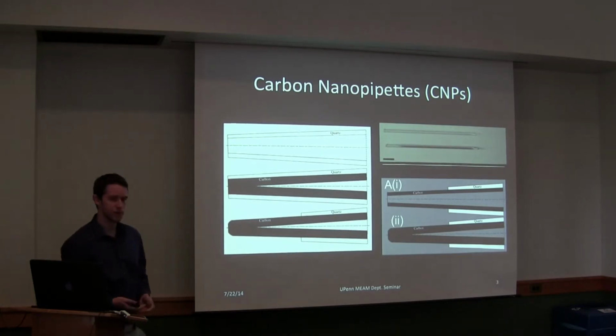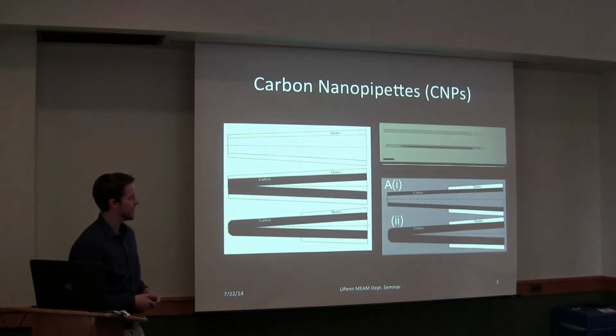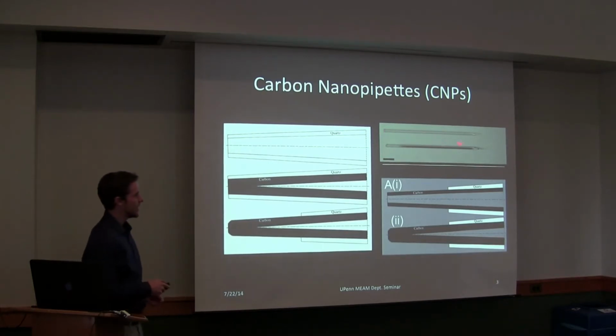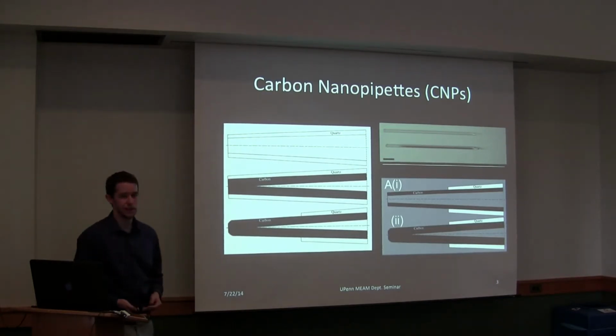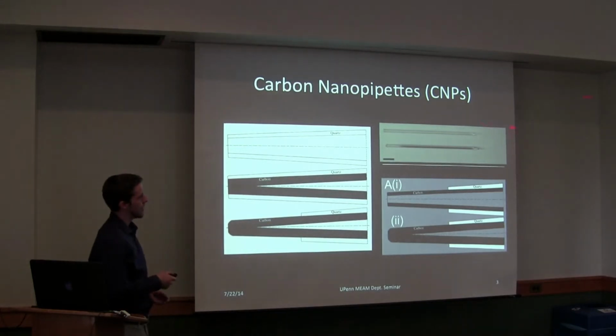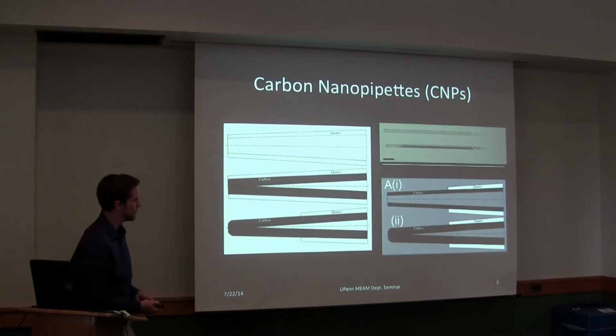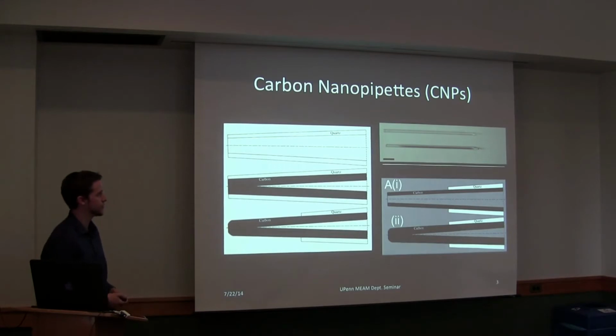There's commercial equipment available to pull these pipettes, and the benefit is that you get a fluidic channel from the macro scale, so the pipettes are on the order of millimeter scale, and the pulled tip can get down to the nanoscale. So you have this continuous fluidic pathway from macro to nanoscale. We then take these pulled quartz capillaries and put them into a chemical vapor deposition furnace at very high temperature.